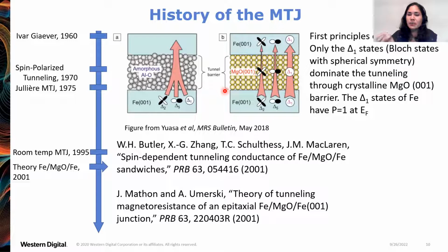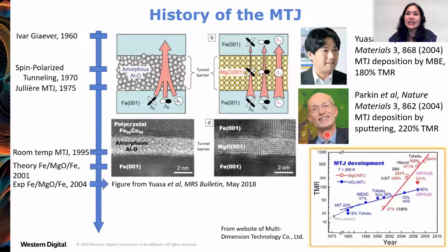And for these fully spin polarized electrons in the MgO, you'll get a lower tunnel barrier height, letting it be easier for them to tunnel. So this combination could lead to TMR ratios approaching 1,000%. So this was very motivating for experimentalists getting better and better at making high quality magnetic tunnel junctions. And sure enough, just within a few years, published in 2004 in the same issue of Nature Materials, there are demonstrations of very high values of TMR with MgO tunnel barriers at room temperature.